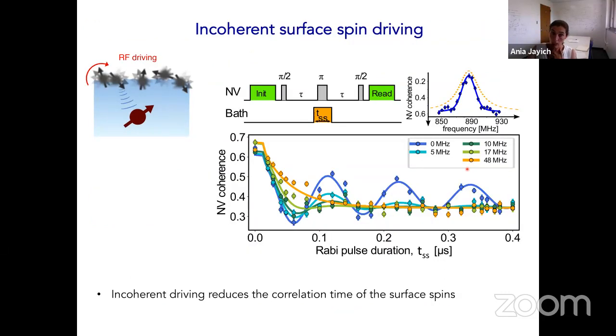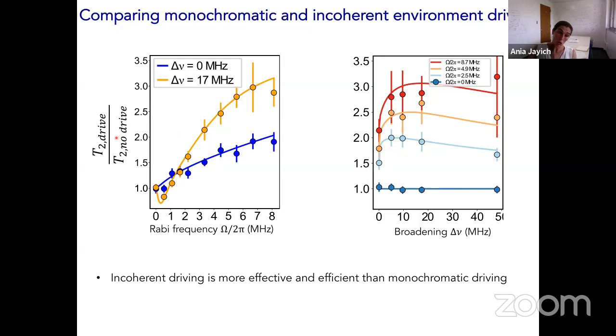We've also recently done incoherent surface driving, where we've driven the surface spins with a drive that has a bandwidth that's broader than the width of the surface spins. These just show the Rabi oscillations of the surface spins, and this is just showing that as we increase the bandwidth of our drive, we're actually dampening the surface spin Rabi oscillations. We're reducing the correlation time of the surface spins. And if we look at the T2 of the NV center with this incoherent drive, as opposed to no drive on, we see that the coherence time increases up to a factor of 3. That's what's plotted in yellow.